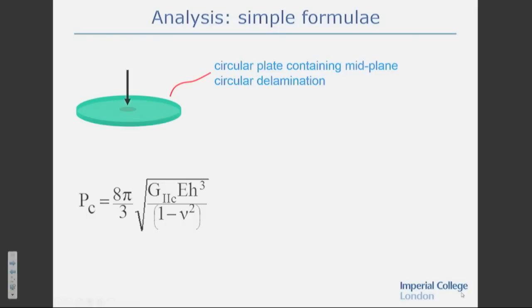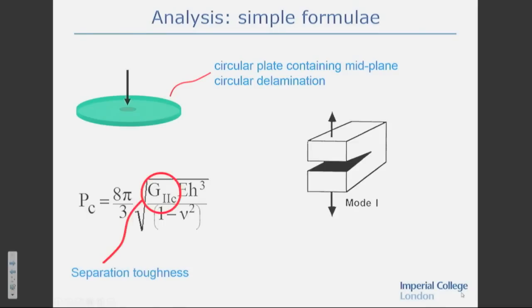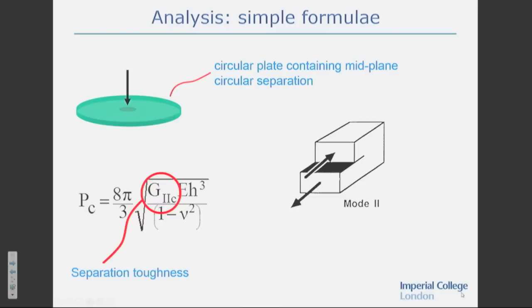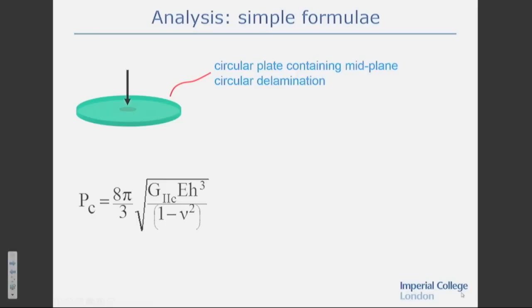The E is the Young's modulus, and this nu is Poisson's ratio. It's to do with the stiffness of the material, and we've already been talking about material stiffness. The H is the plate thickness, and this G2C, well, we already talked about a G1C, remember, it was the separation toughness. That separation toughness we talked about before was in this mode, where we were pulling the two parts apart in this opening mode. But this separation toughness is for a sliding mode that drives the separation. The formula is interesting, of course, because you notice it doesn't have the size of that separation in it. Now let me show you what we were using it for.